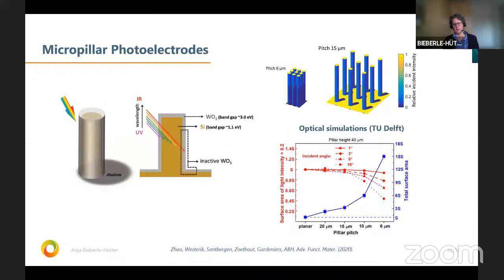And for this, the first idea was, yeah, okay, we get some shadowing if the layers are very close together. So this is for sure one reason that you get shadowing. But also we figured out that we have some inactive tungsten oxide layer, because if we irradiate with an angle, then the tungsten oxide on the back side is not just the real shadowing, but it's really inactive here. So it's like a, I don't know, dead layer or something like this. This is the reason why the performance increase is not as good as we expected.